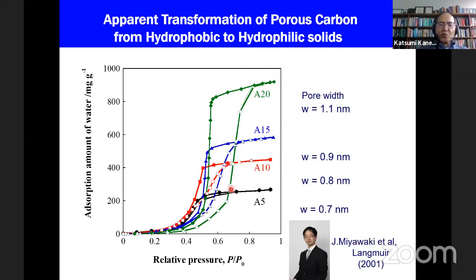But here I will show you our data. This is the water adsorption isotherm on activated carbon fibers without oxidation, but of course with some slight amount of surface functional groups, as a function of the pore width. For example, for this A20 sample, suddenly adsorption starts around here. Then nearly 0.9 gram of water is adsorbed, and then it is not so desorbed, showing very remarkable adsorption hysteresis. But at first, almost no adsorption, hydrophobic, but suddenly hydrophilic behavior. So this is very questionable.